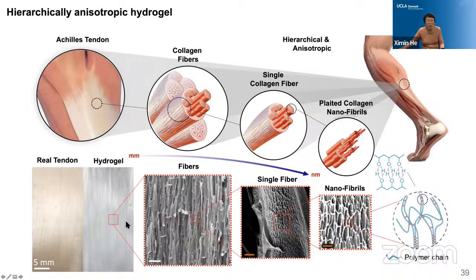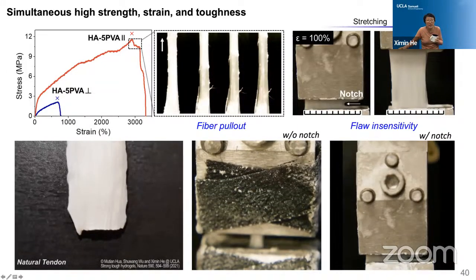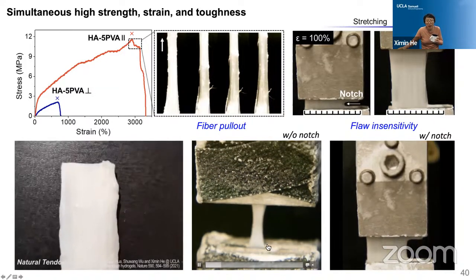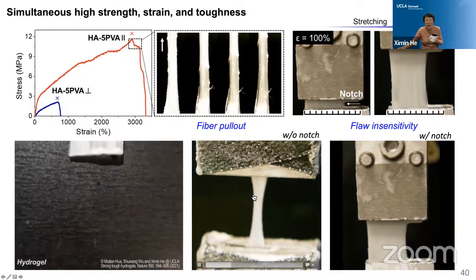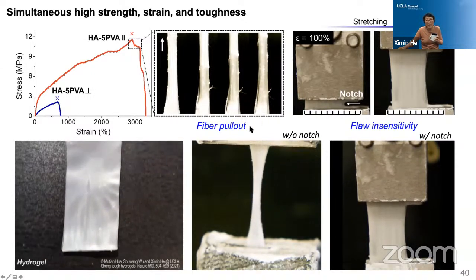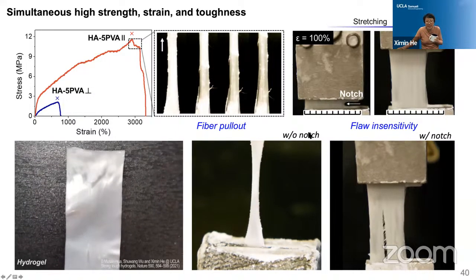So under the SEM, we are able to see that we form these microfibers through the directional freezing, and on top of a single fiber, you can see this nano mesh structure arising from these hydrogen-bonded polymer chains. And if you look at that sample microscopically, it looks very similar to the real tendon that my student purchased from the butcher store. So with this, we measure the mechanical properties, and you can see the samples without a notch or with a pre-cut notch are both very stretchable and with very good flaw insensitivity.